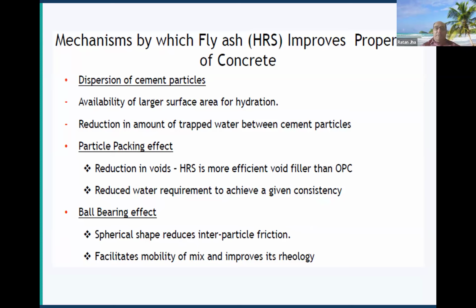Reduce water requirement to achieve a given consistency. Ball bearing effect, that I will show in... Spherical shape reduces interparticle friction, and due to this interparticle friction, at early ages, some stress will develop and concrete structure cracks. But in case of PPC, due to ball bearing effect, the interparticle friction is significantly reduced, and the stress is ultimately reduced, and there is minimal chance of cracks at early ages.